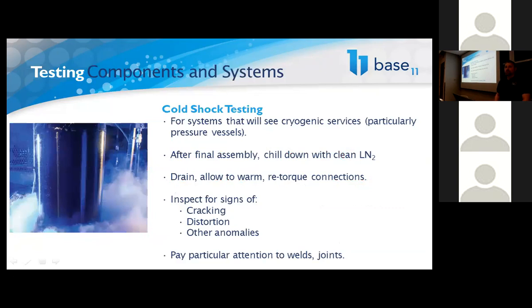Something else that you might want to do, especially for something like a liquid oxygen tank, will be cold shock testing. So this is very common for cryogenic systems, where you will assemble your system and then do an initial chill down with usually liquid nitrogen. Always making sure that the liquid nitrogen you're testing with is properly clean so that you're not introducing any contaminants to your system. Once you've chilled it, you can then drain it, allow the system to warm up, retorque any fittings, and then inspect for any obvious signs of cracking or distortion or other potential damage.